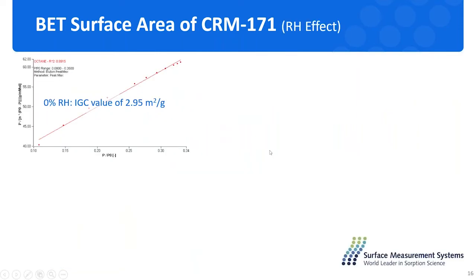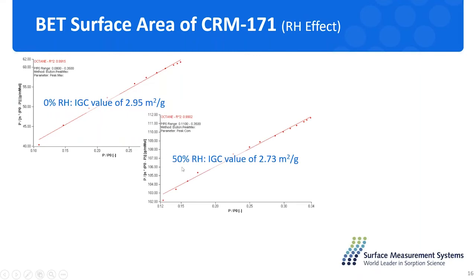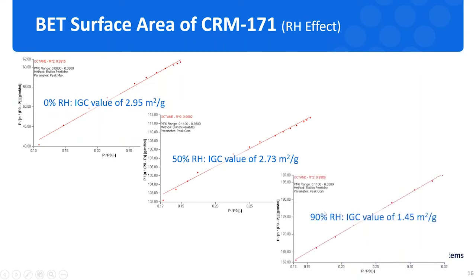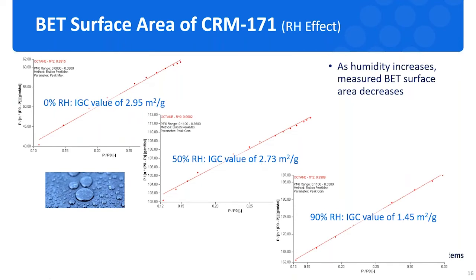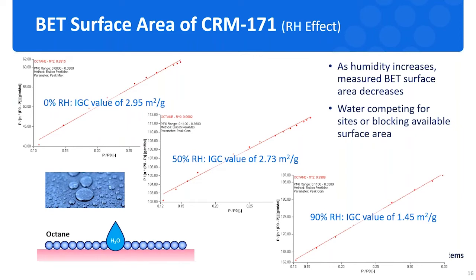And then we performed another study to see how the humidity will affect the surface area of this material. So at 0% humidity, the surface area of this alumina sample is 2.95 square meter per gram. And with the increase of humidity up to 90% RH, the surface area of this alumina sample drops almost half of the original value at dry condition. So basically, with the humidity increases, the BET surface area of this material drops a lot, and that's because the water molecules compete with the organic vapors and also block the available surface area for this kind of material. So the humidity effect on this material is decreasing surface area with increasing humidity.